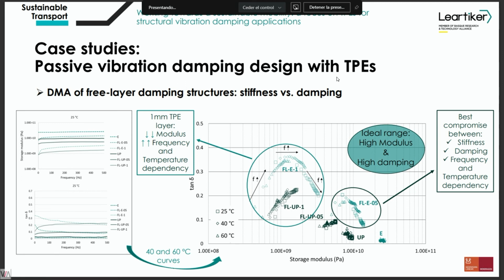For that, it is very interesting to compare the loss factor with the storage modulus. These kinds of graphs are known as wicket plots and give a lot of information when comparing different materials in terms of the target viscoelastic properties. In that case, as I mentioned, the ideal range for the component is high modulus and high damping.